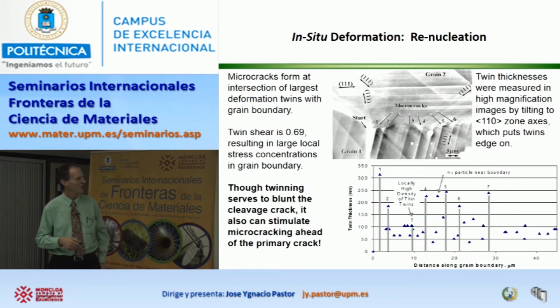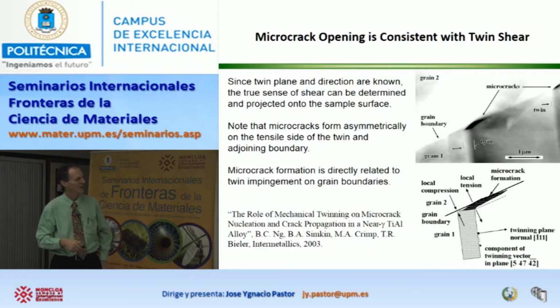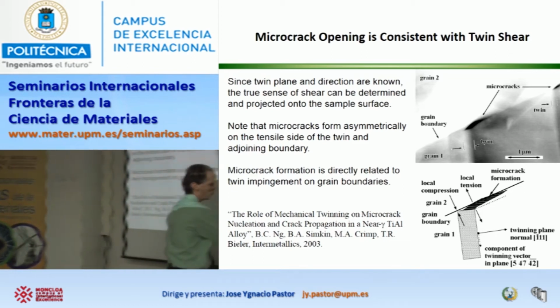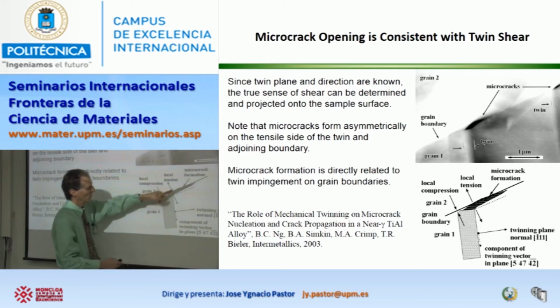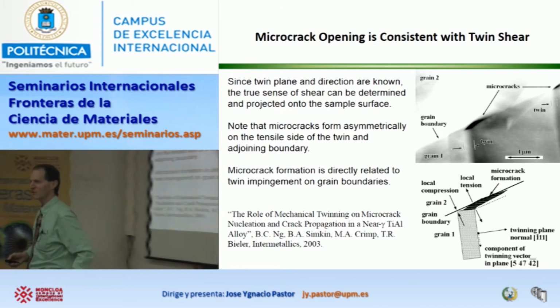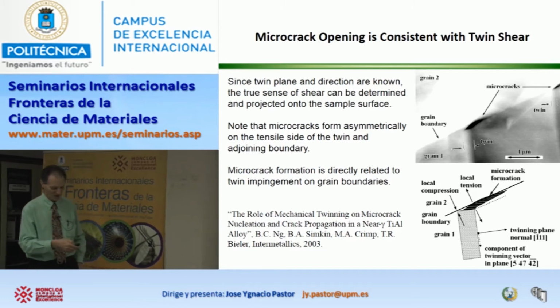And so if we look at where these cracks are located and the thickness of the twin, that's the vertical axis, and then this is distance going from this triple junction to the right. There's lots of little twins, and there's some bigger twins. And the ones that are cracked are the ones that are bigger. So the thicker they are, the more of a shear displacement there is. And here we see that. Here's a crack that has opened up on the side, in the direction in which material has been shifting. So right here, the shear sense of the twin is this way, and hence we're pulling material away from the grain boundary. And so all the cracks have that same shape.